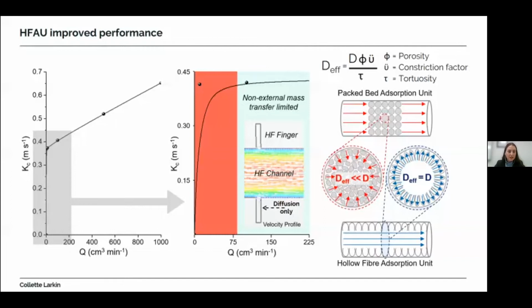And then looking at residence time distribution, deviations from the ideal flow patterns, such as stagnant regions, typically arise in packed bed systems and cause the performance of the system to be lowered, whereas for a hollow fibre adsorption unit, the residence time distribution should be close to ideal due to the empty channels of the hollow fibre adsorption unit minimizing the possibility of deviation from the ideal flow pattern that typically takes place for the packed bed.